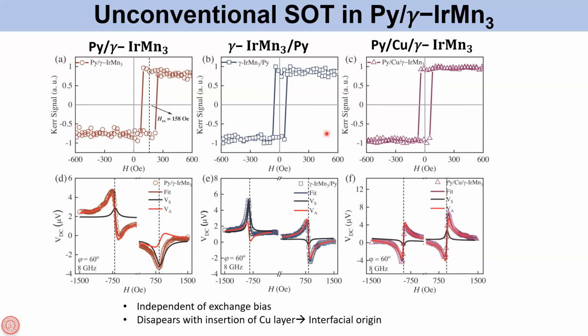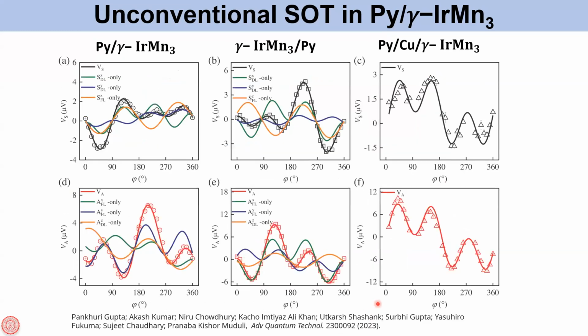So this indicates that the unconventional torque that we observe here is of interfacial origin, because it happens only when the permalloy is in direct contact with IrMn3, and it is independent of the sequence. Independent of that means it is independent of the exchange bias as such. So this is an indication that this is of interfacial origin. We further verify this by means of detailed angular dependent measurements of the symmetric and antisymmetric components, where you see that there are significant deviations from the sin 2phi cos phi dependence, both in the symmetric component and the antisymmetric component, whenever the permalloy is in direct contact with iridium manganese. Doesn't matter the stack sequence.